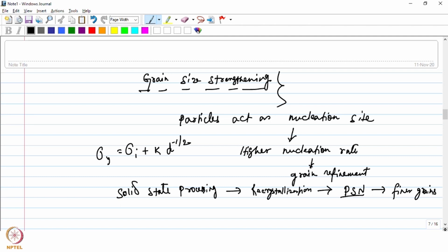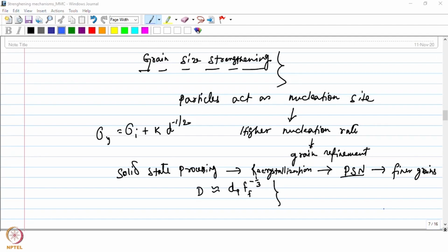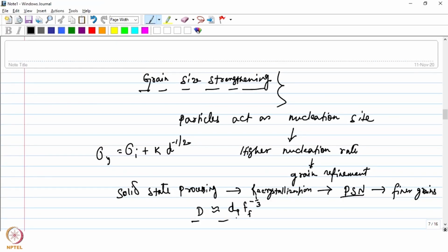The resultant grain size D can be approximated by this particular expression, where dP is the particle size and F is the volume fraction of particles. Right, so this can even happen during solid state processing also.